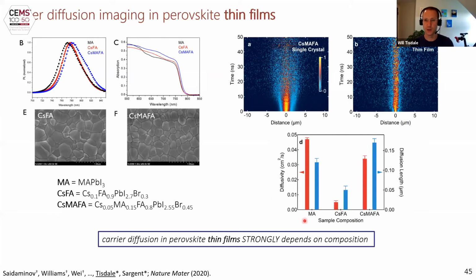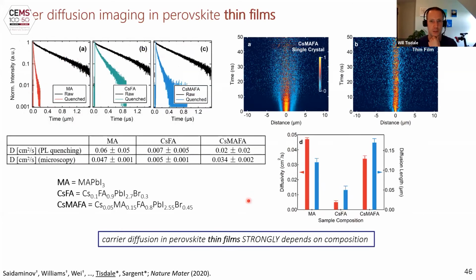the data. So in all cases, these are the same 3 compositions, but in thin film form this time. In all cases, the diffusivity is an order of magnitude lower than it was for the single crystal. So that's telling you that the grain boundaries already are having a role in disrupting charge carrier transport. And we saw much greater variation among the different compositions. So the carrier diffusion in the perovskite thin film strongly depends on composition.